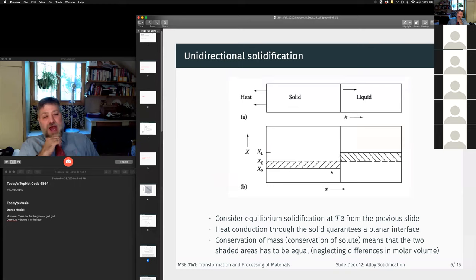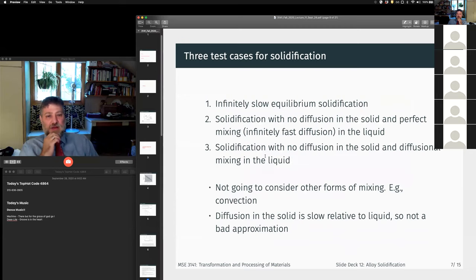From a conservation of mass point of view, we're not creating or destroying any solute. Our atoms of our alloying elements are not going away, and we have no nuclear reactions transmuting them from one element to another. So what that means is that any solute that is rejected from the solid into the liquid has to be balanced by an increase in concentration of the liquid. So that means that these hatched areas have to be equal. So there's a balance of compositions that has to happen here, okay?